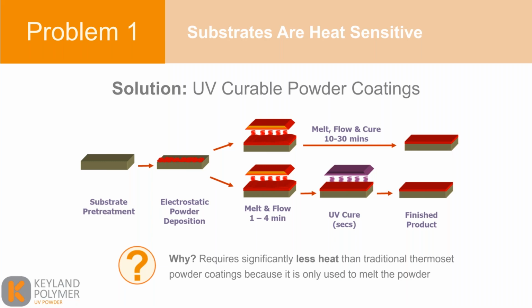Comparatively, with UV curable powder coatings, the powder looks exactly the same. However, it has photoinitiators within the coating itself that react to ultraviolet light. So the powder is applied electrostatically. It needs to melt and flow, so it needs to get to an elevated temperature of around 110 degrees C, which can be achieved in 1 to 4 minutes. After it's exposed to a high intensity ultraviolet light, we're utilizing UV LED technology now, which does not apply additional heat onto the substrate, the coating is then cross-linked and cured, and you have a finished product. So as you see, what I've laid out is that it requires significantly less heat than traditional thermoset powder coatings. And the goal is to only melt the powder.